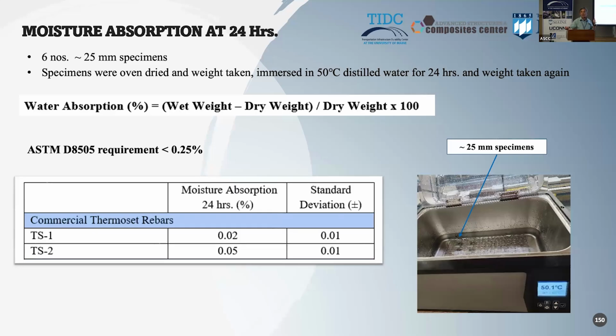And this is important because any degradation related to exposure can be, for example, salt water, can be water in an alkaline environment, can be freeze-thaw cycles. Anything where water plays a role in degrading properties will depend on the ability of that polymer to absorb moisture. So that's why we need to limit that percentage.